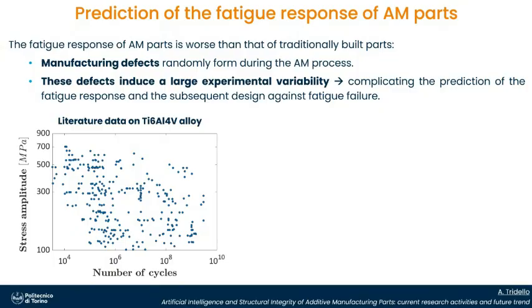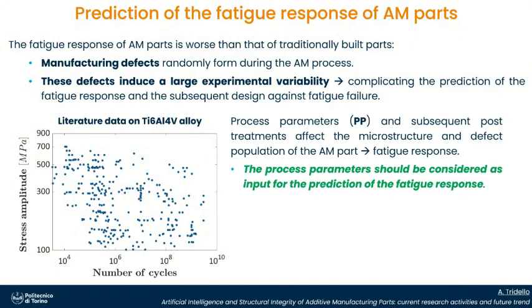And these defects induce a large experimental variability. You can see some experimental data taken from the literature for a titanium alloy, and you can see that there is a large scatter. This complicates the prediction of the fatigue response and subsequent design against fatigue failures. But what is responsible for this variability? For example, process parameters and post-treatment affect the microstructure and the defect population, and so they affect the fatigue response.